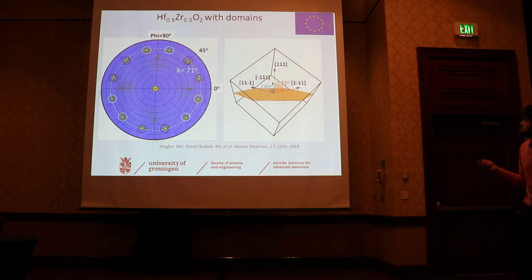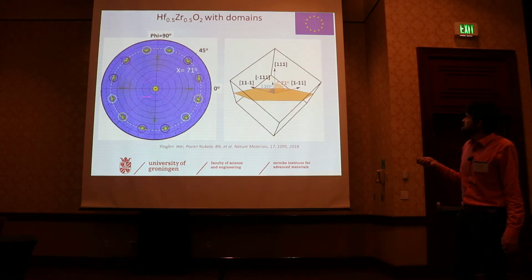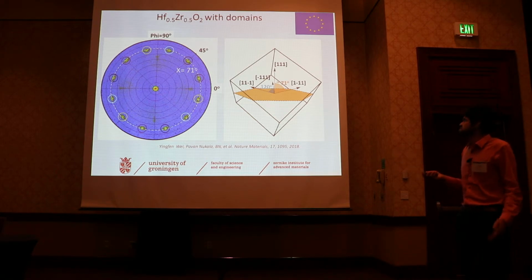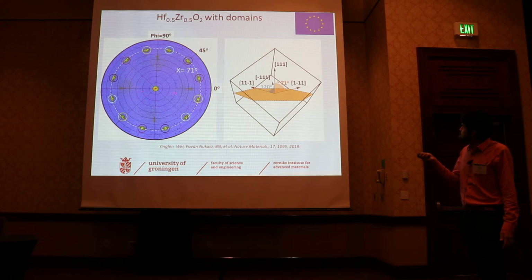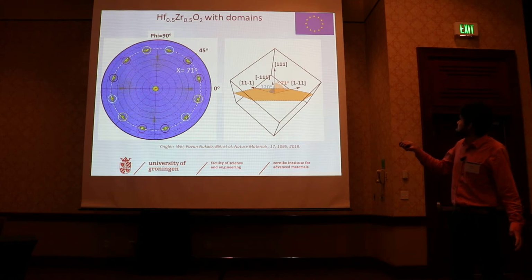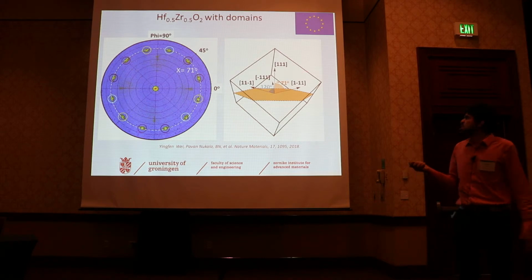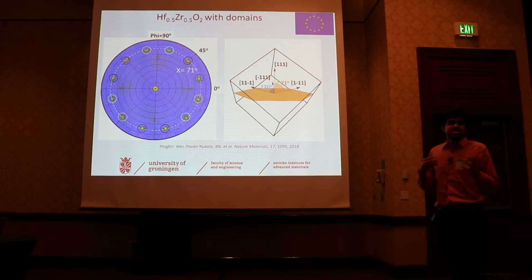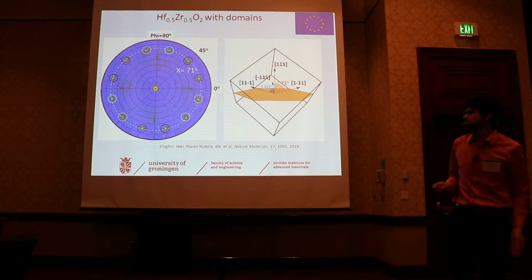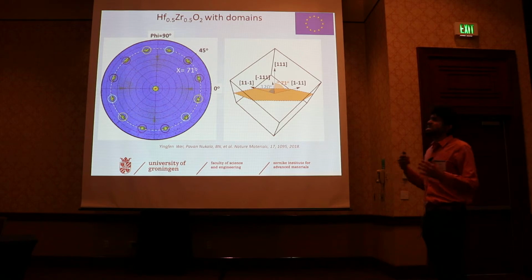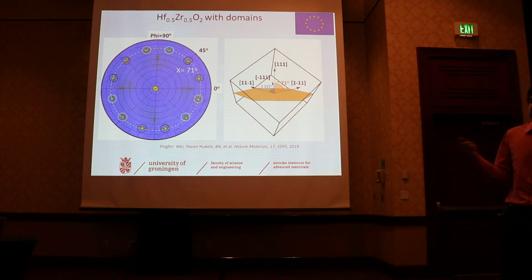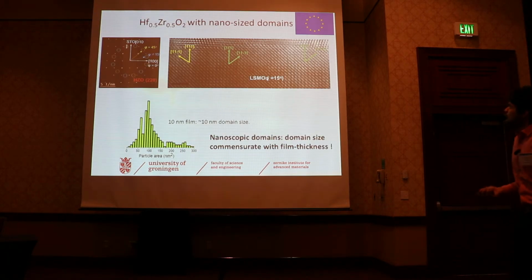All right, so we did some pole figure analysis to see the texture of the films. Around the pole that is out-of-plane 111, ideally you have to find 3 poles if it is a single domain film, but we do find 12 different poles, which suggests that there are 4 different domains which are rotated at 90 degrees with respect to each other. So we do have multi-domain single-phase films when you make these films as thin as possible.